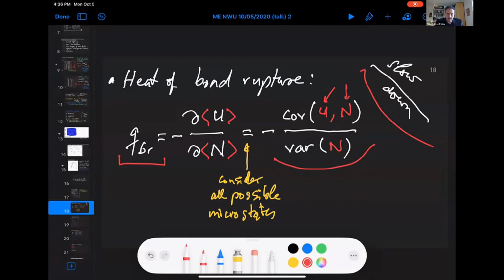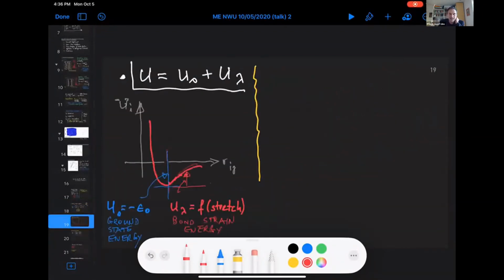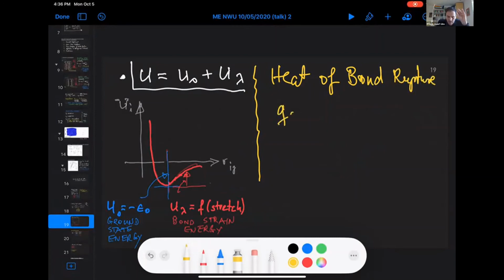Now, let's be clear about it. What does that basically mean? So here, that's basically the energy. The heat of bond rupture here, I will write in the form that we can make the difference and the link with classical fracture mechanics. So Q_BR is equal to minus the variation of U with regard to N, ensemble average, right? But this is also minus Q_BR zero, the heat release due to ground state energy, and then minus the heat associated with strain, lambda.